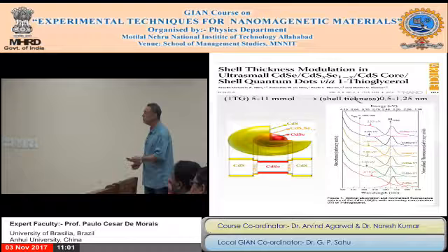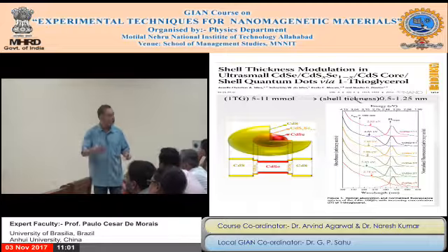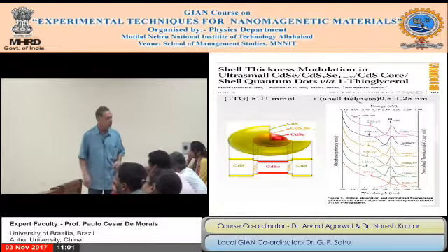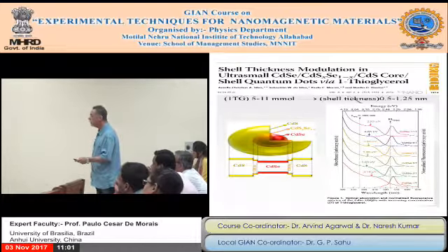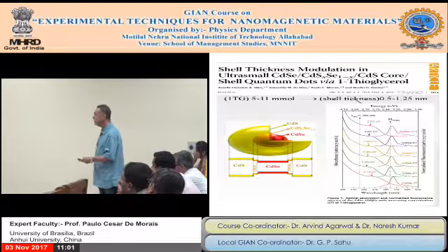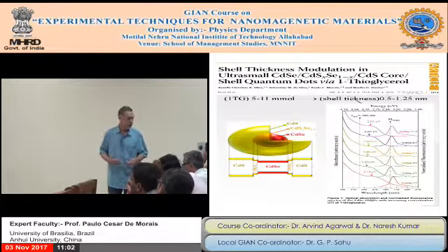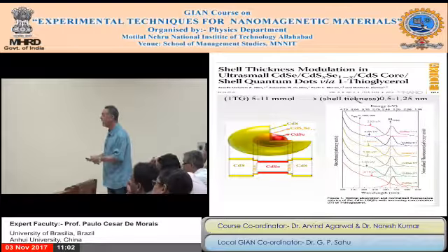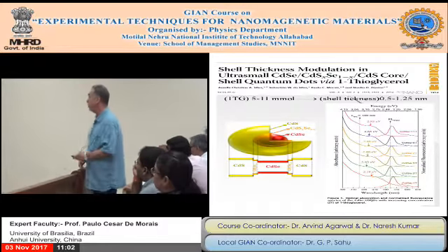Cadmium sulfide has a wider gap, cadmium selenide a narrow gap, and then we can build a quantum well like this. But the layer in between has a gap between cadmium sulfide and cadmium selenide, which is alloying. It depends how wide the gap is. It depends on the composition, the X composition. Okay?